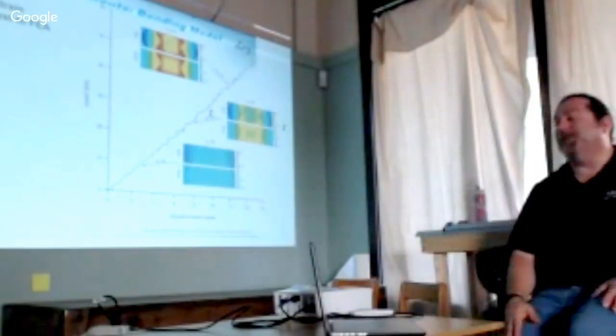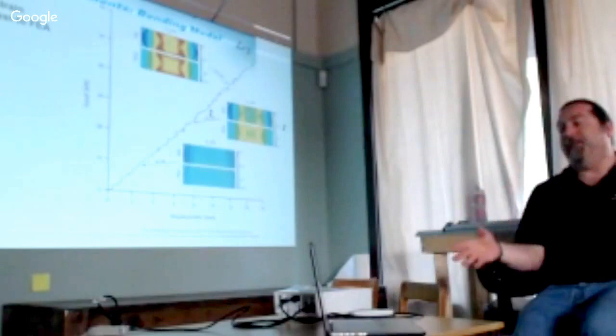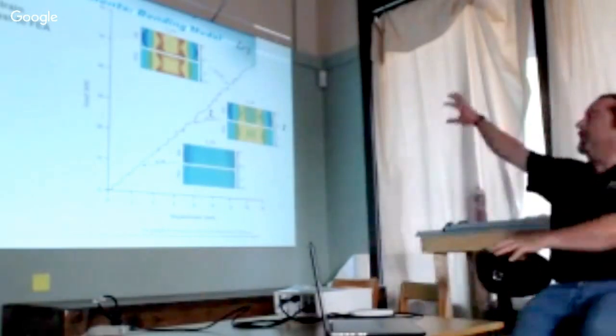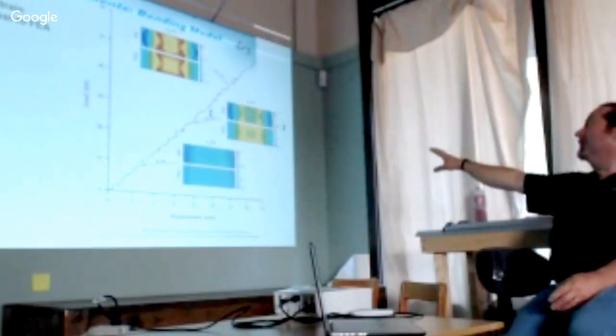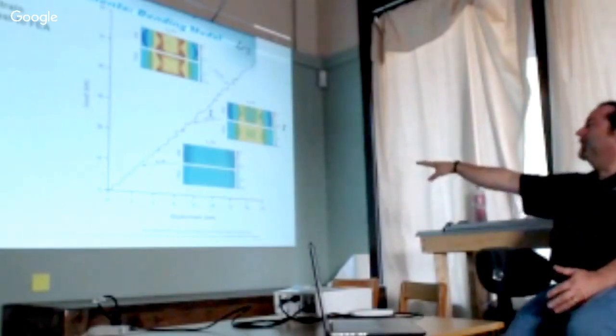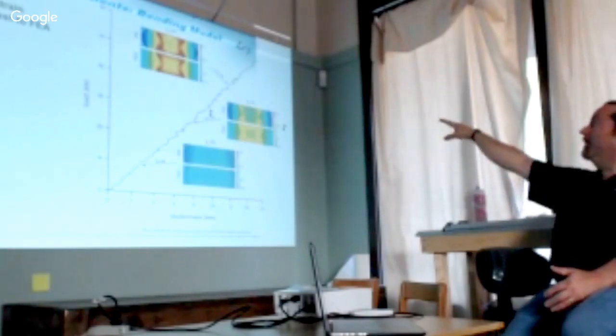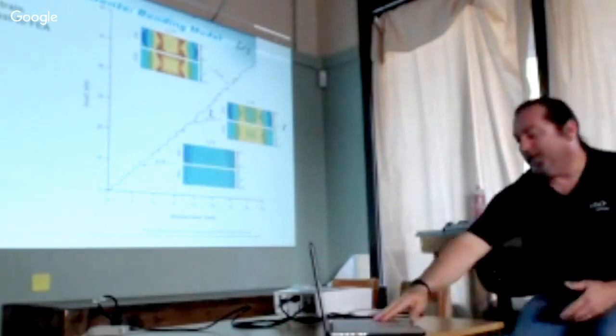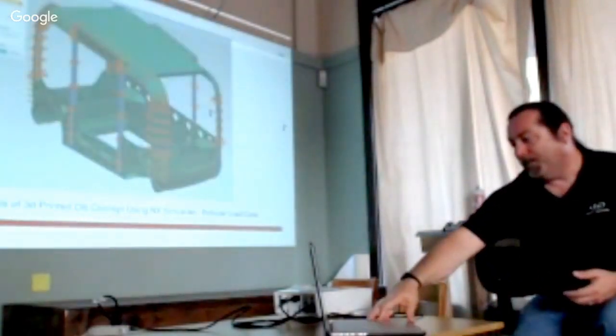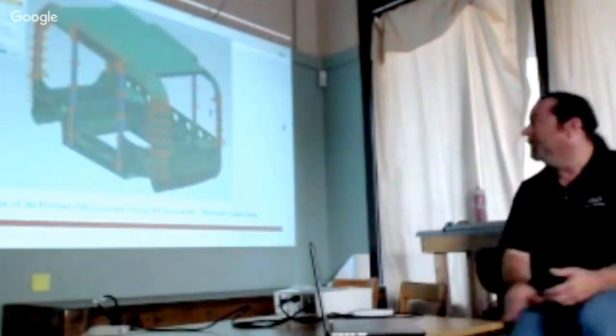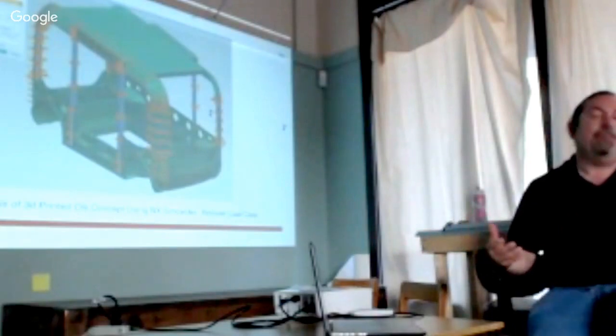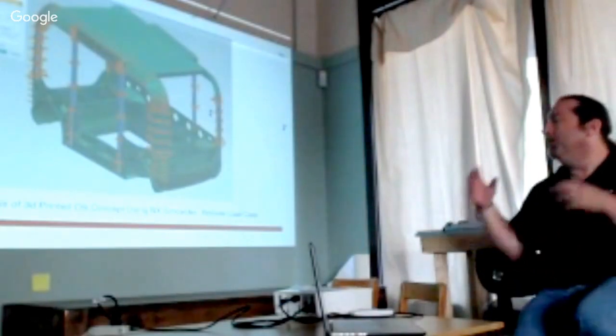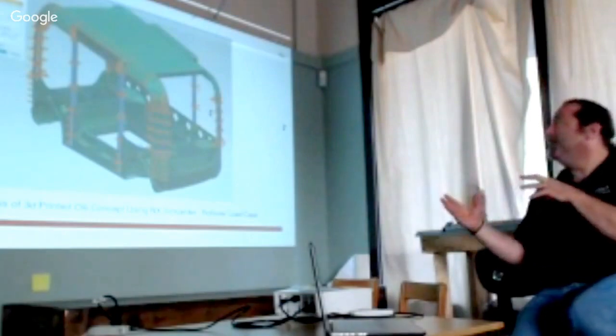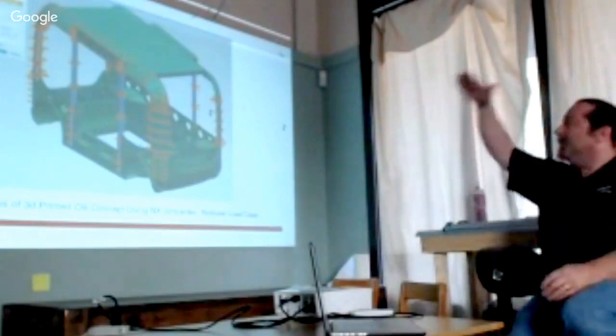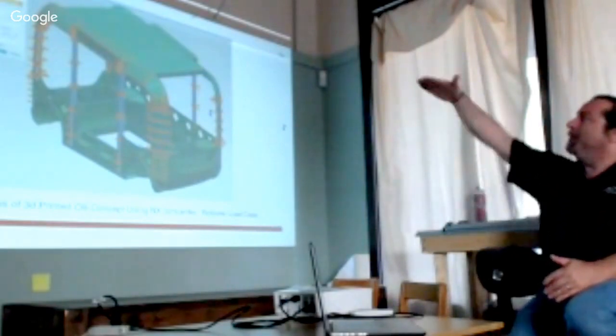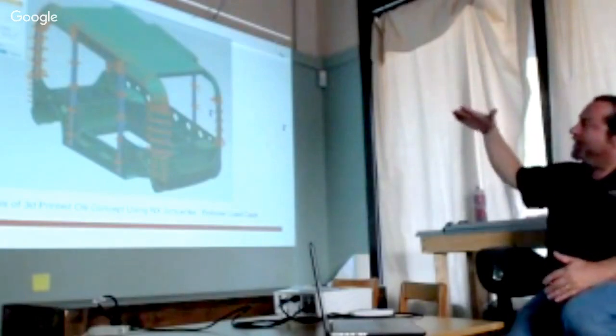And here's some of the results actually comparing the DIC strain measurement to FEA results, at different stress levels. It's that same bending test we were looking at, with the FEA result below and the DIC result above, and we really did have very good correlation comparing those surface strains. And now we're applying that to the full 3D printed Olli structure. This is just a real quick simulation I did over the weekend. This is a rollover, applying a 45-degree, 7,000 pound distributed load on that corner.